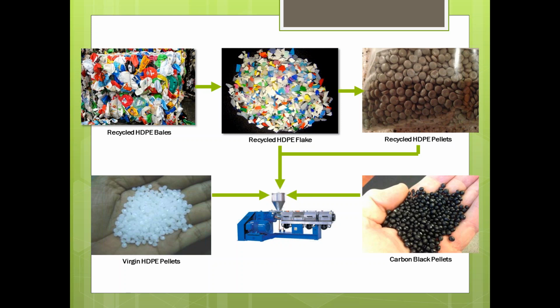It'll include obviously the recycled flake or pellets. It'll include usually some portion of virgin pellets, and it will typically include a carbon black pellet or an antioxidant packaging that goes along and inside with the blend to make sure that you provide that antioxidant protection for long-term service life. One of the difficult things to quantify with recycled plastics is how much antioxidant packaging is left in the remainder of the post-consumer ground resin. So adding in that antioxidant packaging is critical towards long-term service life and performance. And that's what really reinvigorates and really juices the blend to be more applicable for long-term service life applications.